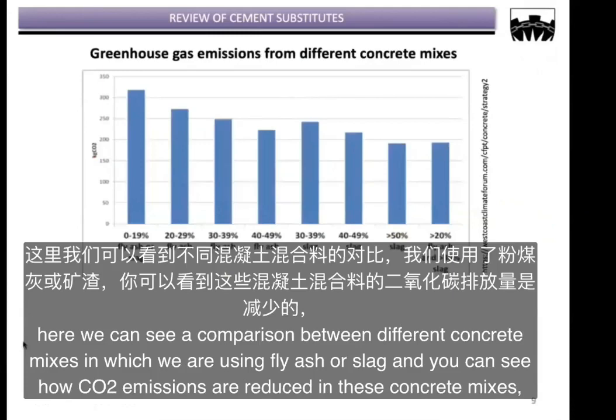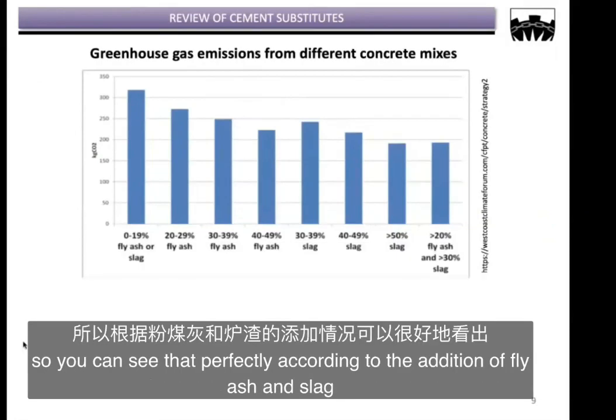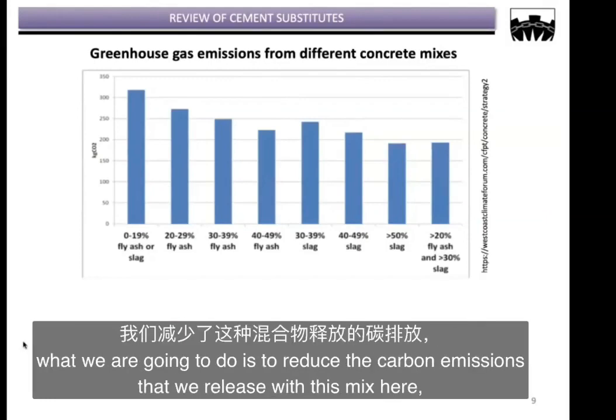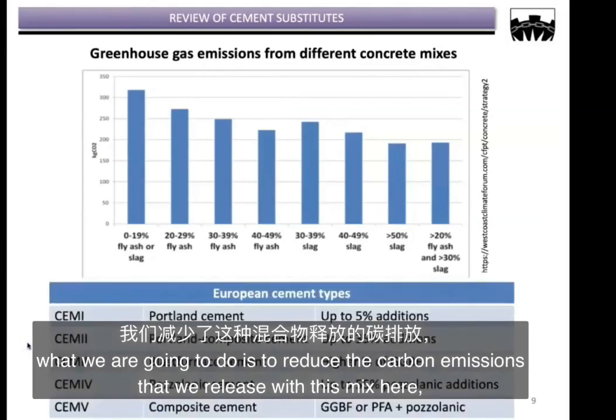Well, here we can see a comparison between different concrete mixes in which we are using fly ash or slag, right? And you can see how CO2 emissions are reduced in these concrete mixes. So you can see that, according to the addition of fly ash and slag, we reduce the carbon emissions that we release with this mix.